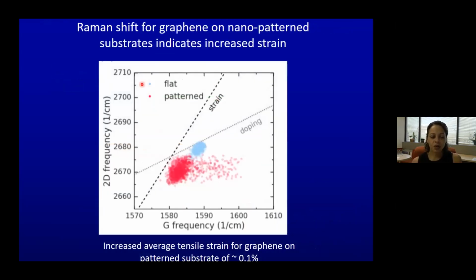Okay, we looked at the ratio of the 2D to the G frequency. When you look at the ratio of the 2D to the G, you can see that this line here is the factor of 2 line that shows how things should move if they're strained. And this line here is the 3/4 line that shows what the ratio should be for doping. Okay, and then we took flat graphene right here. We started here. And then we patterned the graphene, we moved here, and you can see that we moved along a line. Okay, it's red. We moved along a line in that direction, which, as you may note, is parallel to the strain line.